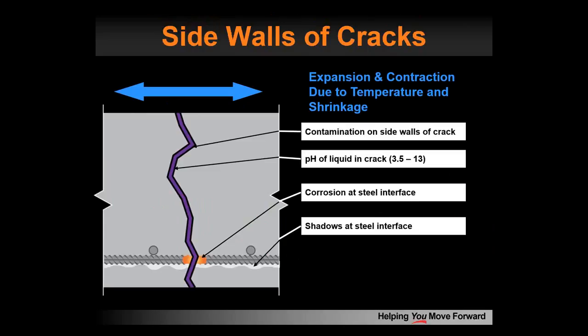One of the things that you do need to understand is that when you're going to inject any type of grout into a crack or joint in concrete to make it monolithic, many times these cracked sidewalls are contaminated with clays, with silts, with carbonates, with a whole variety of different types of material. So if you have a structure that's been leaking for a long time, the cracked sidewalls may be contaminated, and anything that you try and inject in there is really not going to bond that well. It'll give you some fairly immediate surface sealing, but with time, if the cracked sidewalls are contaminated,